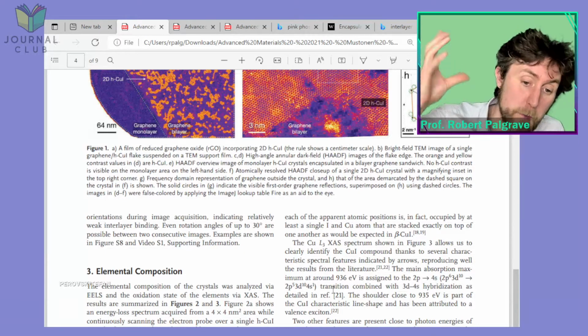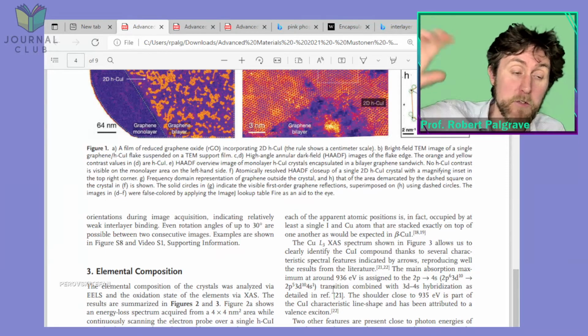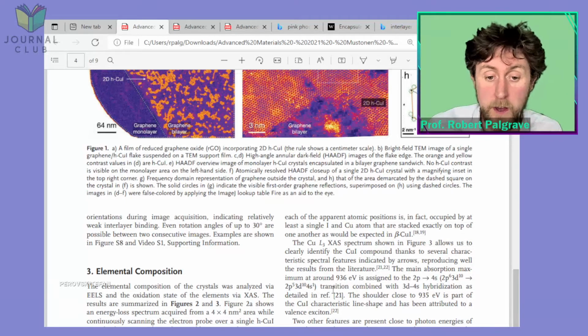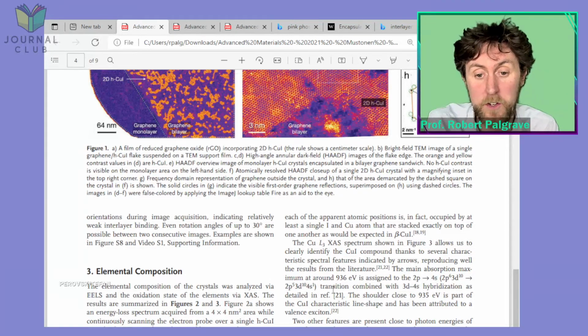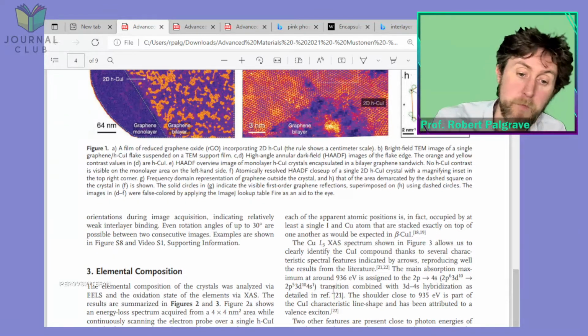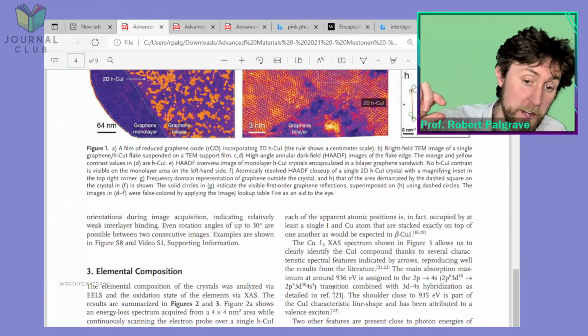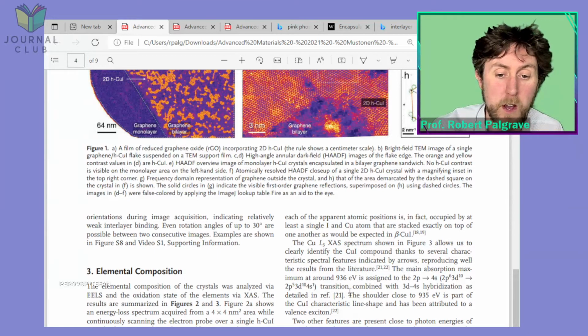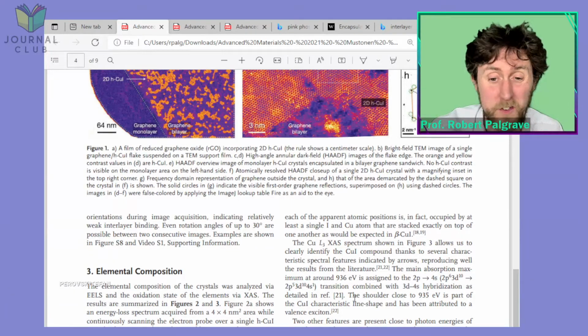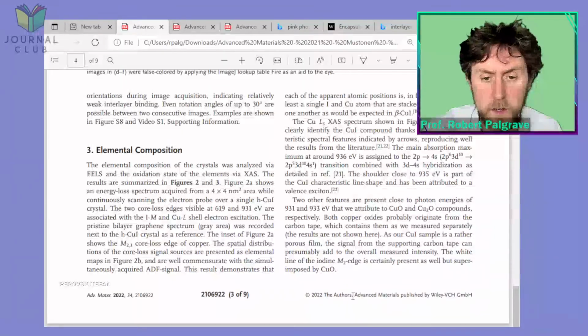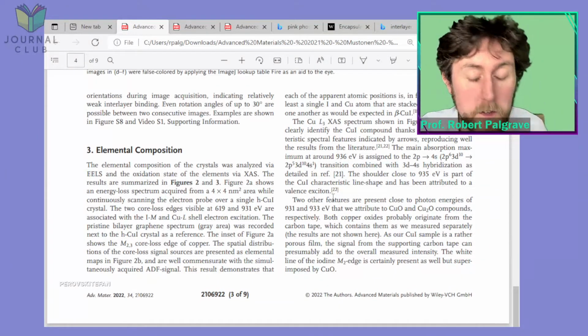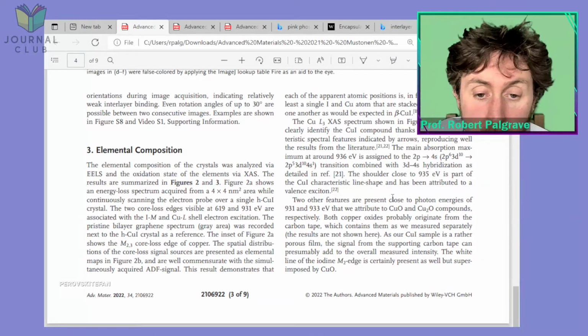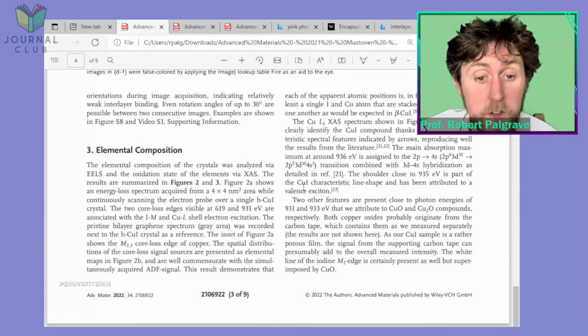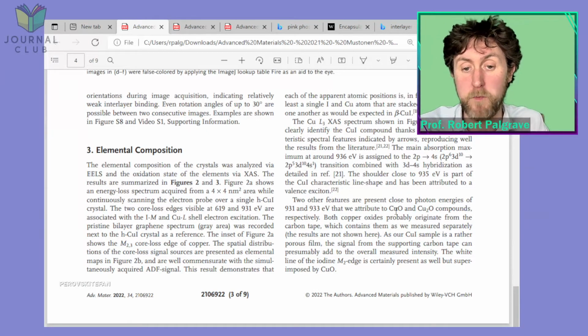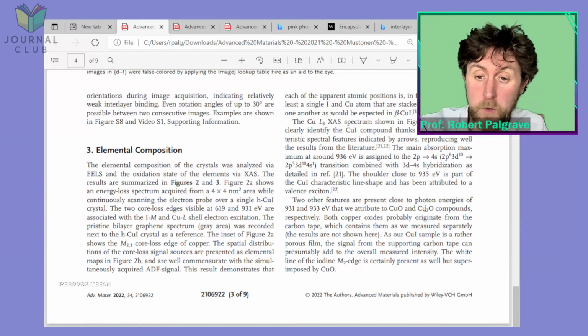So what we're talking about here is the electronic structure, the arrangement of the outermost electrons and the empty electron energy levels within the material. I think that would change quite dramatically going from the cubic structure to a 2D layer structure. So that's an interesting point. I wonder whether that comparison really stacks up. I would want to have a look at reference 22 and see what they say there. Two other features are present close to photon energies of 931, 933 eV that we attribute to two different oxides of copper, copper 2 plus, copper 1 plus oxide.